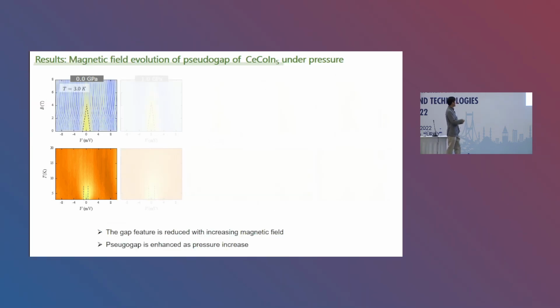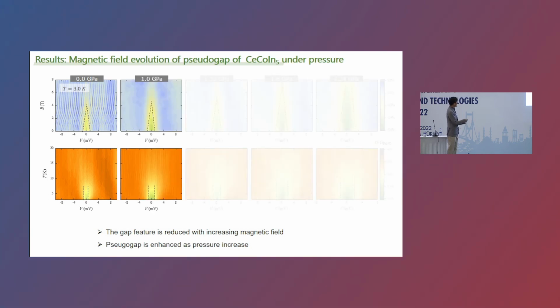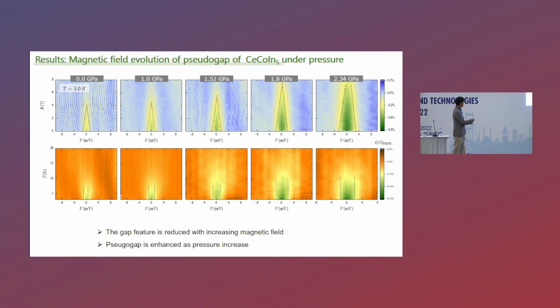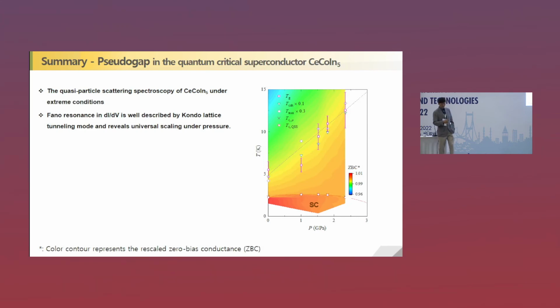And this is a comparison between the temperature evolution and the magnetic field evolution. With magnetic field, unlike temperature, which does not change the gap size, the gap size is suppressed as well as the dip. At 1 GPa, we can see a similar suppression of the gap size with magnetic field, and a similar trend. Okay, since I don't think I have much time, I'm just going to summarize it.